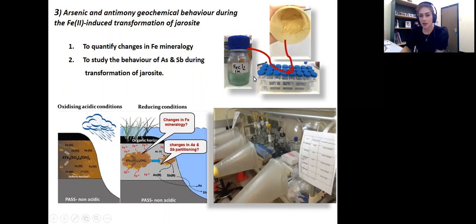So what I wanted to do was add iron 2 to my jarosite suspension. And I wanted to have a range of different pH to be representative of different stages of freshwater reflooding. I had pH 4, pH 5.5, and pH 7 buffered for my samples.